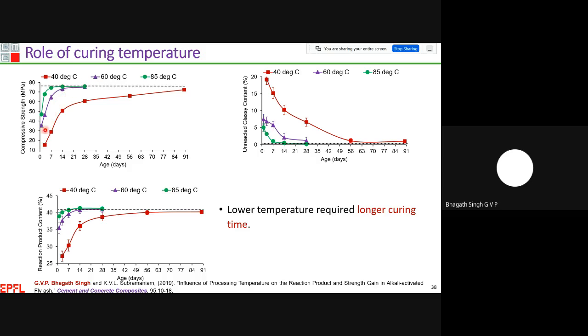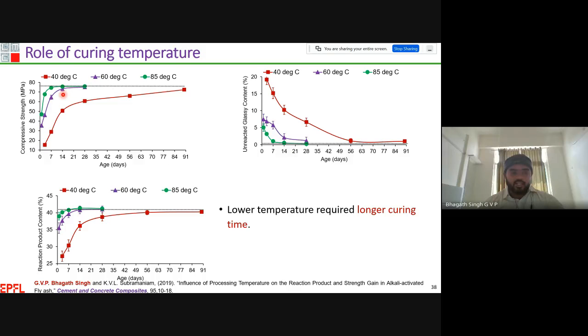In the case of 60 degrees Celsius, I can see a steady increase in the compressive strength till 14 days, and I can achieve the maximum strength by 28 days. But in the case of 40 degrees Celsius, the strength is steadily increasing till 90 days. In the case of lower curing temperatures, we have to wait much longer to achieve similar compressive strength as the other curing temperatures, if you are able to maintain the total reactive oxide ratios the same. You can see these types of trends. If you use different solution ratios, then you will not achieve the compressive strength at 40 degrees. And this is with the pure fly ash system. We have not used any slag and also we have not used any additives.